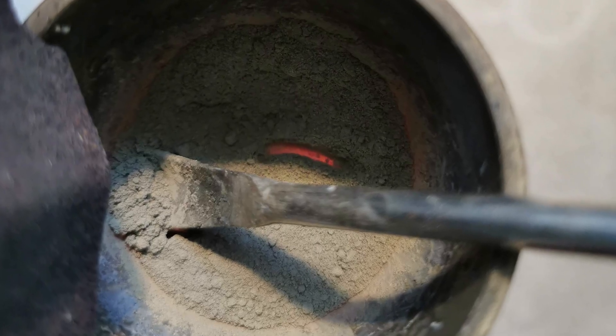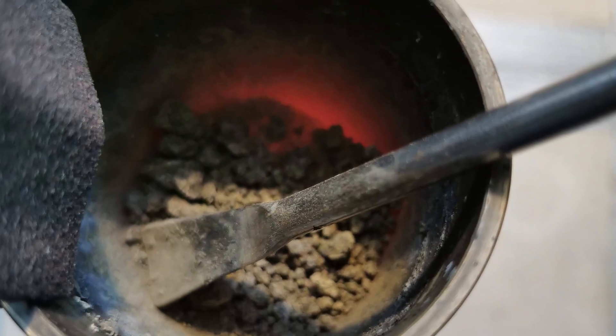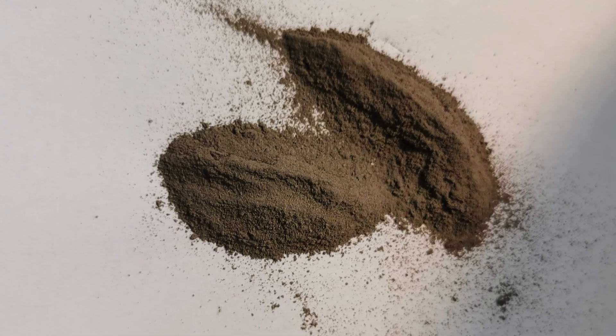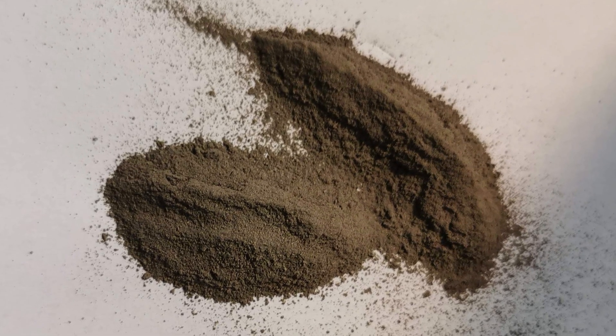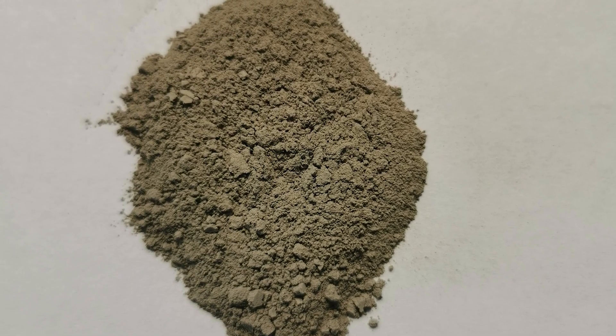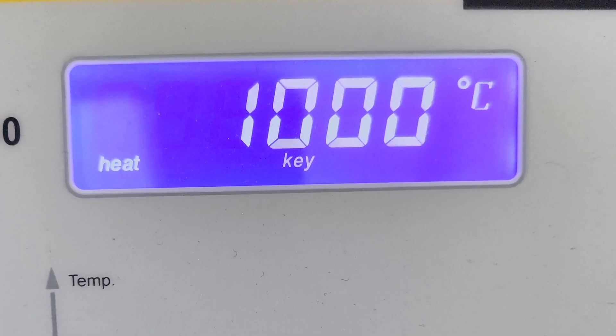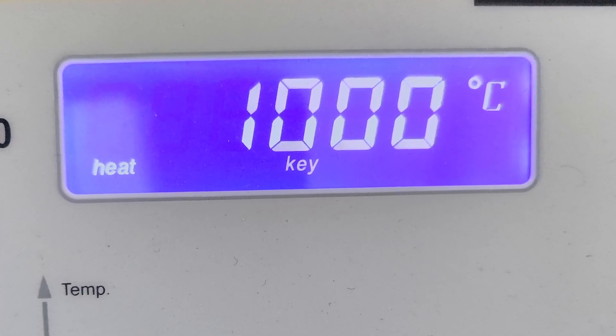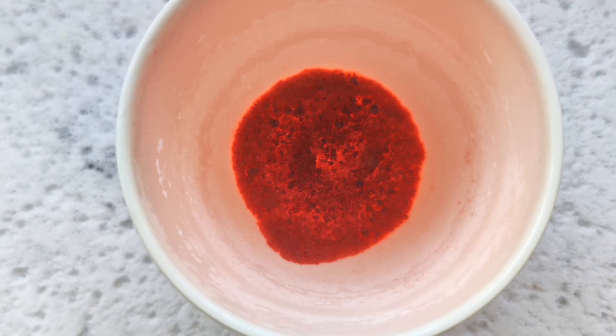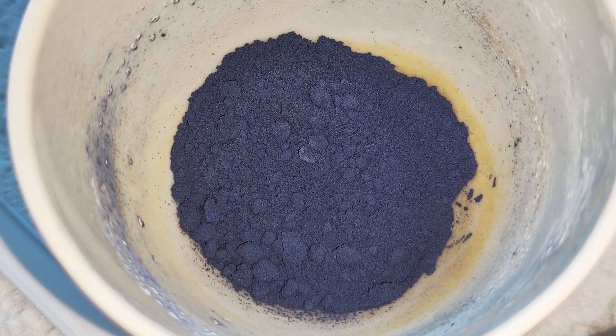I kind of got ahead of myself by trying to sinter the powder right there in the crucible with the burner for half an hour, which obviously didn't work. It probably also made the nickel contamination much worse. So after I let it sit around for a few weeks, I finally got around and put it in a real furnace — first 1 hour at 1000 degrees Celsius and then 5 more at 1100 degrees. In between that I took it out and ground it up some more. After letting it cool down, it looked like this: not exactly vibrant, but rather dark with a bluish hue.